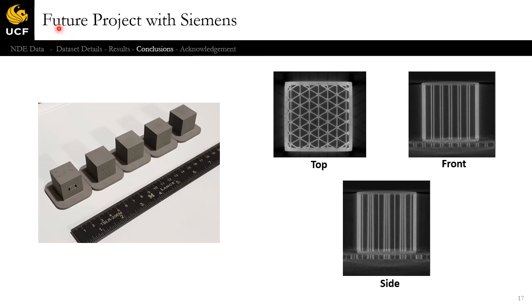I want to talk about our future work, a future project we are working with Siemens on. Essentially we're looking at metal 3D printing. We already have some samples printed - essentially just cubes, some with cooling holes, some with unique geometries. We want to utilize neural networks to tackle the sintering problem. After these metallic cubes are printed, they need to go into the sintering oven and they're going to shrink at a somewhat unknown rate. They don't shrink in a constant or uniform manner based on printing directions. It's very hard to quantify how much these cubes will shrink once they go into the sintering oven. We're going to utilize CT scans and take images of that and hopefully get some method of quantifying the shrinkage or get a better prediction of shrinkage utilizing artificial intelligence and neural networks.